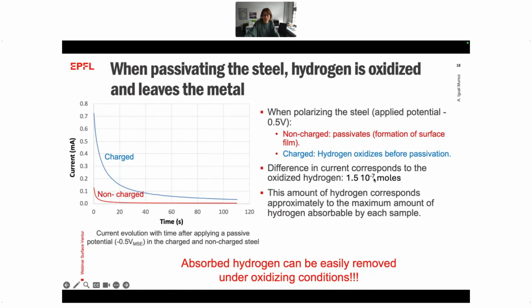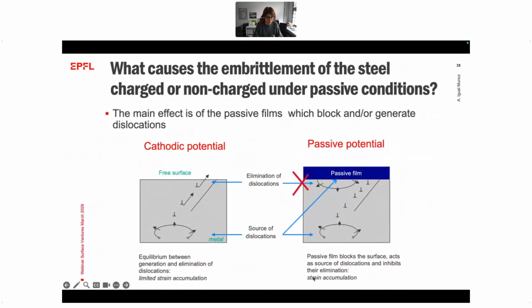And then we can easily calculate this amount of hydrogen, assuming a certain diffusion coefficient, the maximum amount of hydrogen that we can put inside the material. So the absorbed hydrogen can be easily removed under oxidizing conditions. And that means that this embrittlement that we observed during passive conditions was not due to the effect of the hydrogen, but mainly to the fact that you have the presence of a surface film, a passive film, on top of that. This is already known in tribocorrosion. It's called the Rehbinder effect.